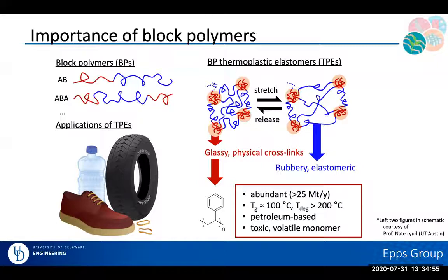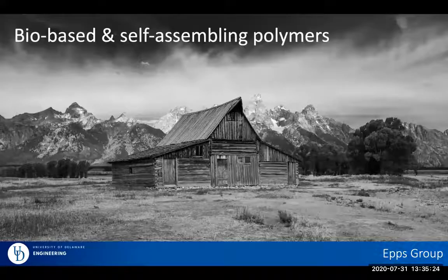In terms of degradation temperature, if we want to be able to melt process our material, we need a substantial region between that glass transition or softening-like temperature and that degradation temperature to provide a nice window for the processing. Now, some of the things that we want to take advantage of are that styrene and polystyrene are petroleum-based. Our materials are going to be bio-based. And styrene is a toxic and volatile monomer. So if we can design monomers that are less toxic and less volatile, that also gives us a potential advantage.